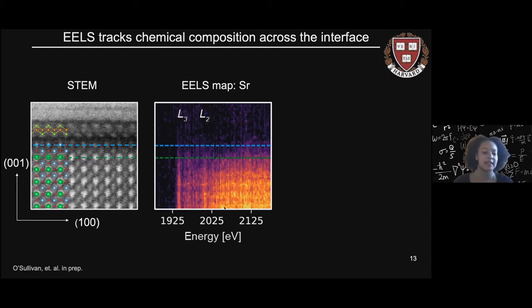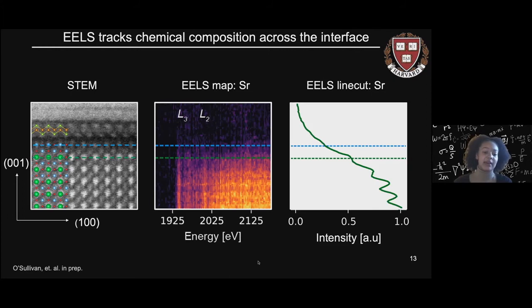You'll note that the peaks in intensity here shown in a yellow color and the lower intensity regions shown in purple or black exactly correspond with where we see strontium in our STEM image, where we see these clearly defined, well-ordered layers of strontium. Moreover, we can directly see these peaks if we conduct an integral and sum over all of the different regions in a line cut, where now our x-axis is intensity and our y-axis is again the spatial resolution. And you'll note that we see peaks in our strontium signal exactly where we see strontium atoms in our STEM image.